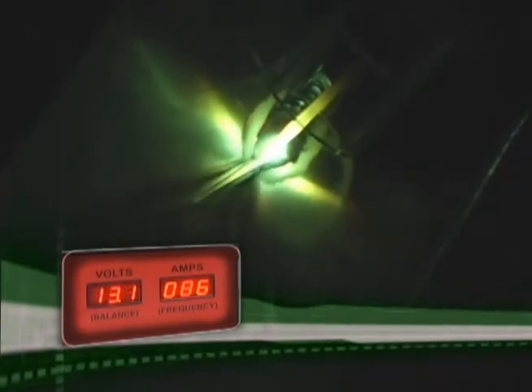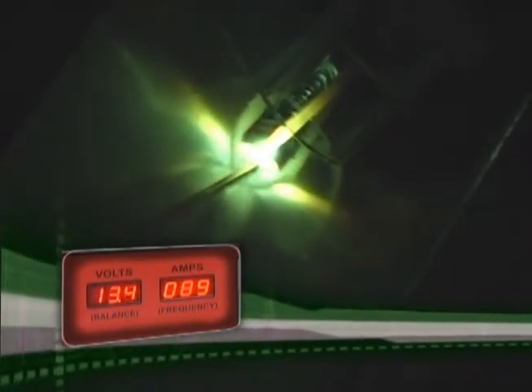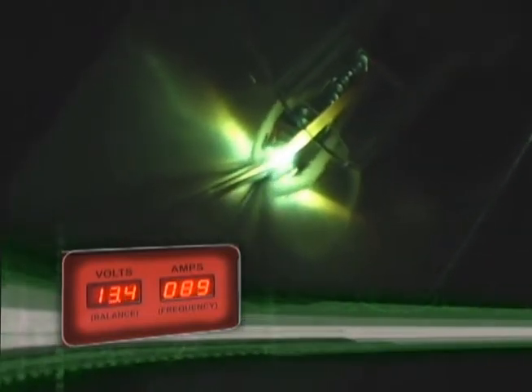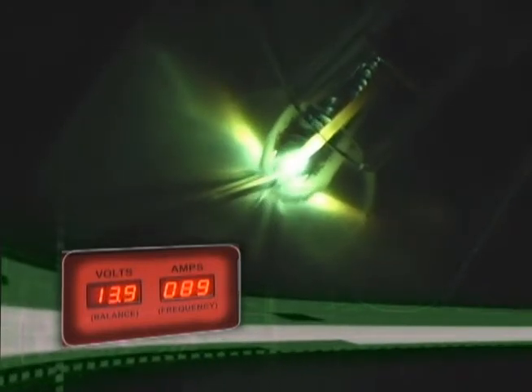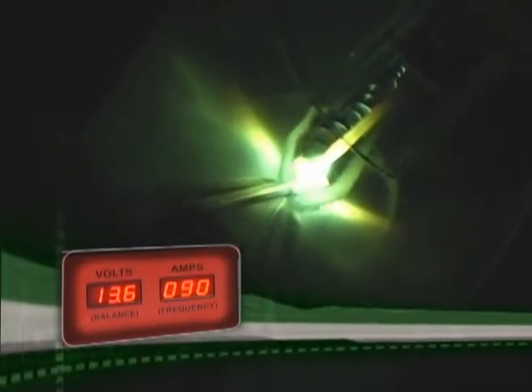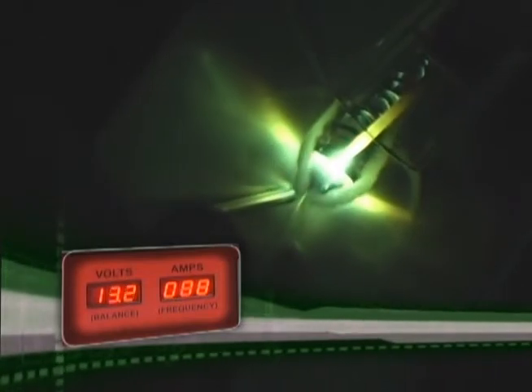As the name implies, you are filling a corner, so you are using more filler rod. You are actually pushing the rod into the puddle versus dabbing it. You want to put enough filler rod into the puddle to make a convex bead.